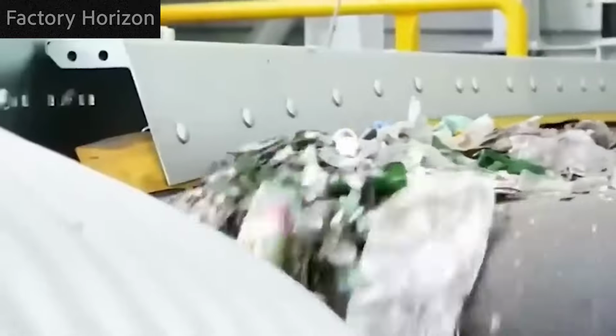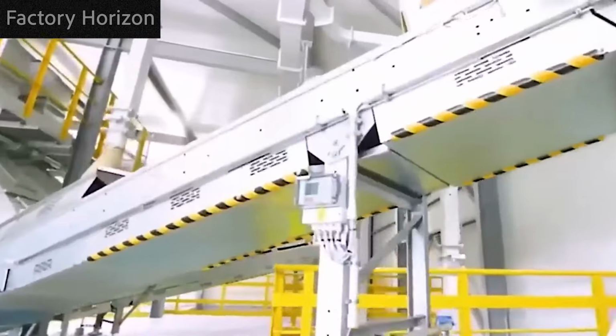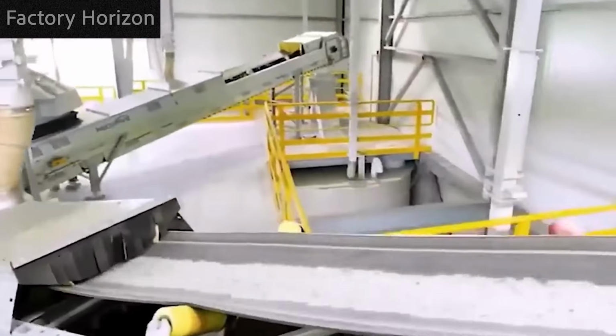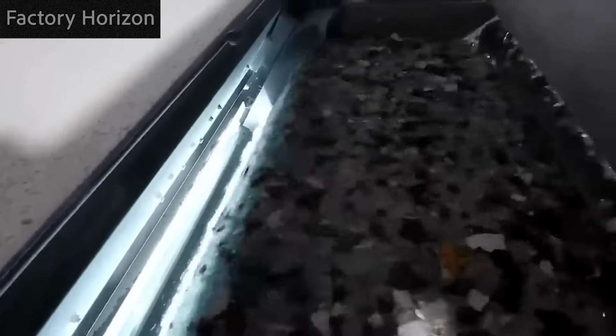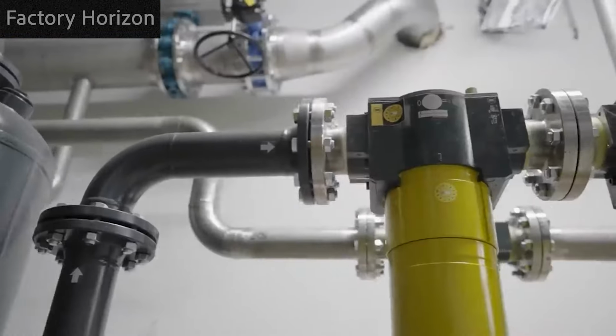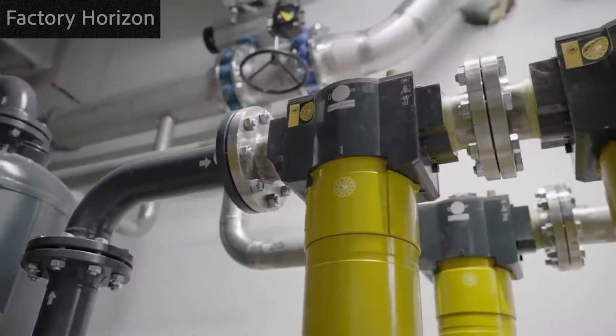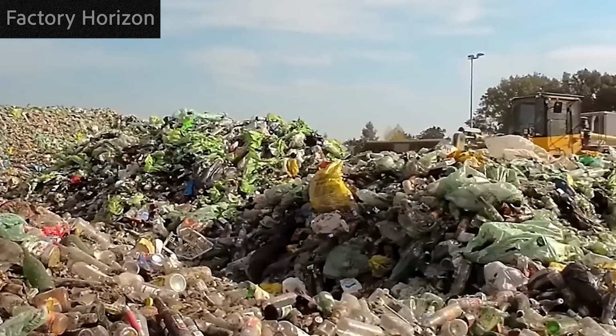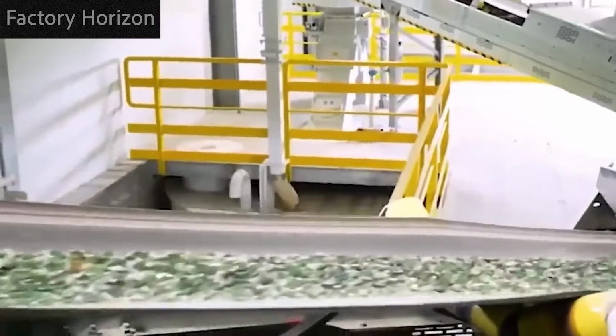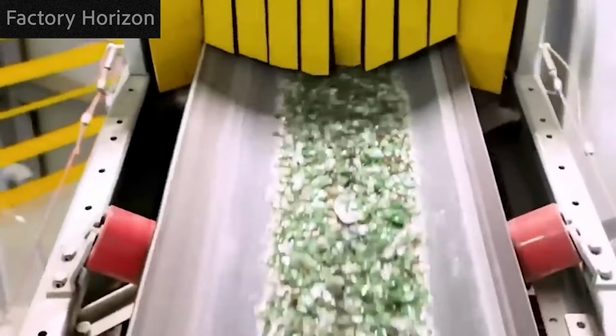They change complete hammer assemblies every 400 operating hours because glass is incredibly abrasive and wears down even hardened tool steel. One set of hammers processes roughly 8,000 tons before reaching minimum thickness specifications and requiring replacement. The crushed cullet flows through magnetic separators one final time in a last-chance contamination removal step. Even tiny metal fragments missed in earlier washing stages get caught now, because when glass melts at extreme temperatures, any metal contamination creates permanent defects and weak spots.